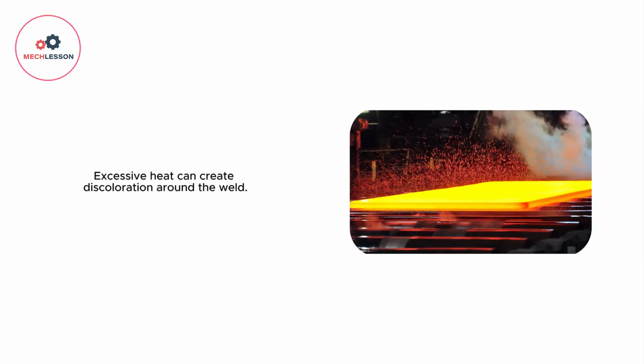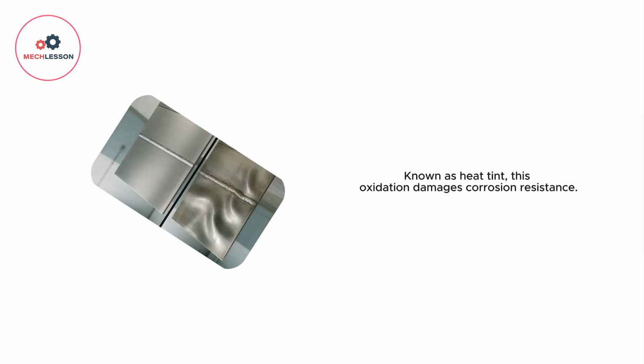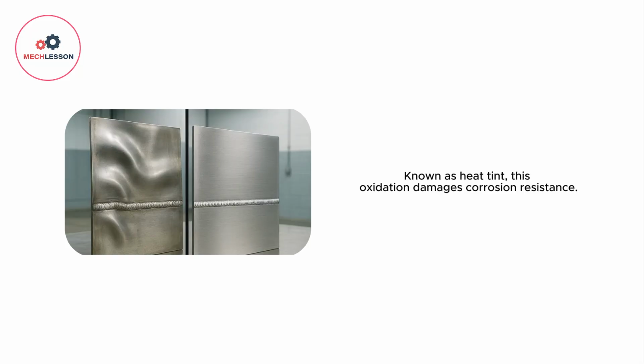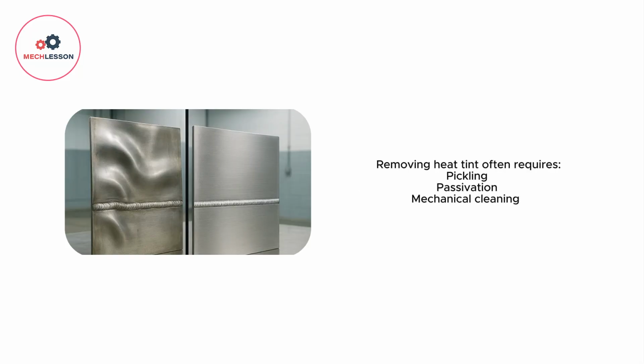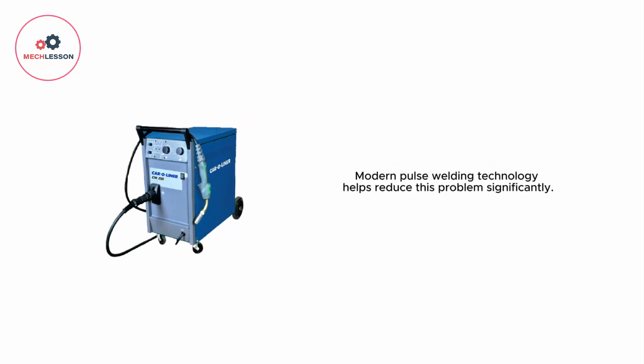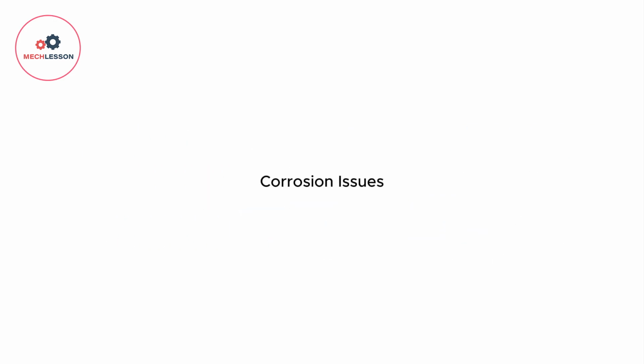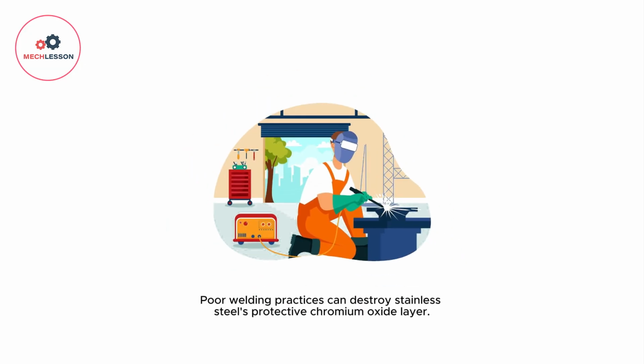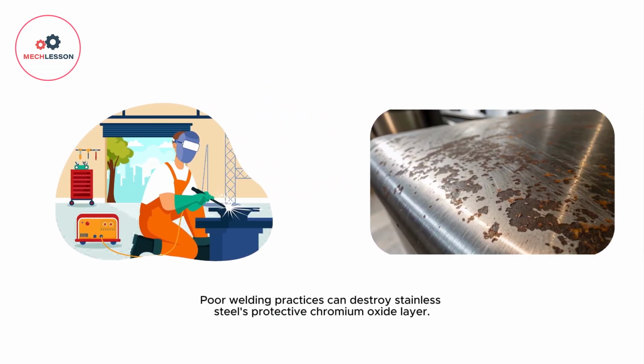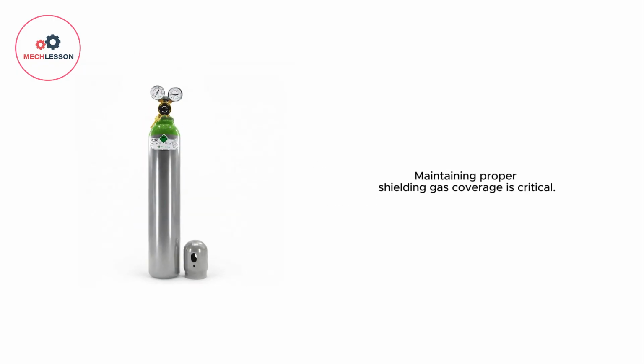Heat tint and discoloration. Excessive heat can create discoloration around the weld. Known as heat tint, this damages corrosion resistance. Removing heat tint often requires pickling, passivation, or mechanical cleaning. Modern pulse welding technology helps reduce this problem significantly. Corrosion issues. Poor welding practices can destroy stainless steel's protective chromium oxide layer. This can lead to rust formation, pitting corrosion, and reduced service life. Maintaining proper shielding gas coverage is critical.